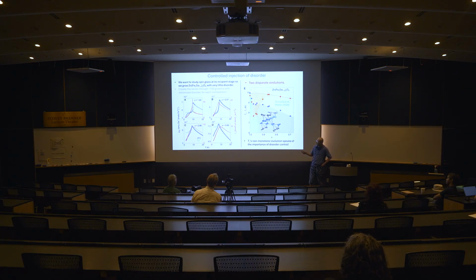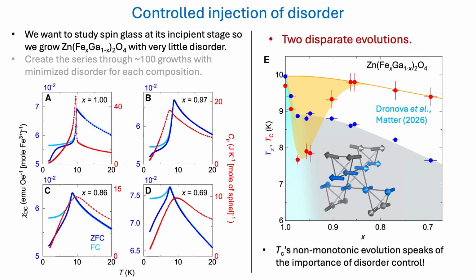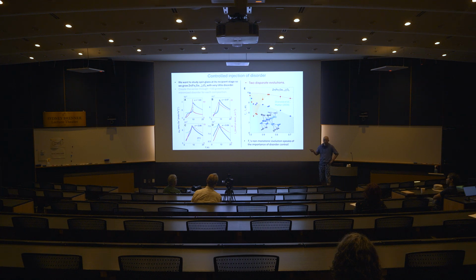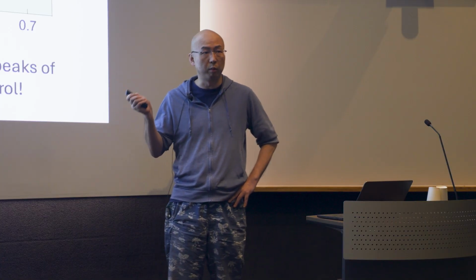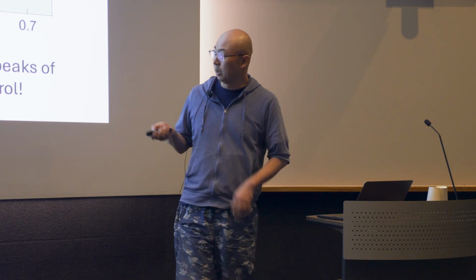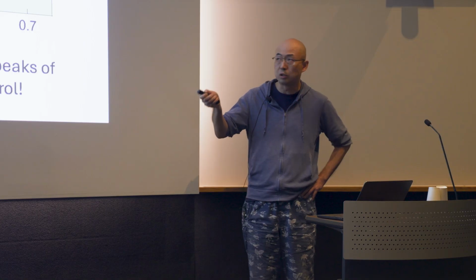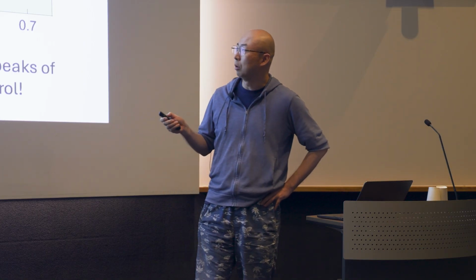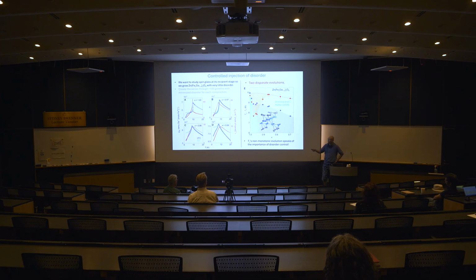Then you put the peak temperature onto this diagram of temperature versus doping ratio. You can see the blue curve has a monotonic behavior like this, but the red curve has oscillating behavior. It's non-monotonic, and it oscillates around the blue curve. So once the doping starts, these two characterizations never appear to be consistent. And the worst part is that it's non-monotonic. You keep wondering, what is the reason for this non-monotonic behavior? However, looking at the position of this valley, you realize it's important to have very good control of disorder, because with a couple more percent of disorder, you might wipe out this whole feature. That speaks to the importance of disorder control, which allows us to observe this oscillation at a very low disorder concentration.